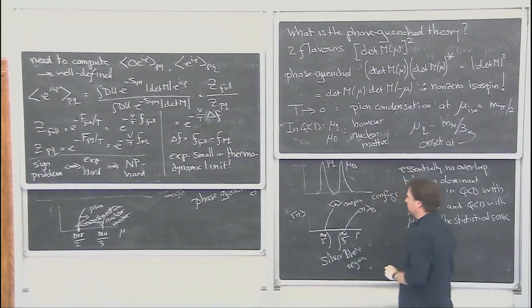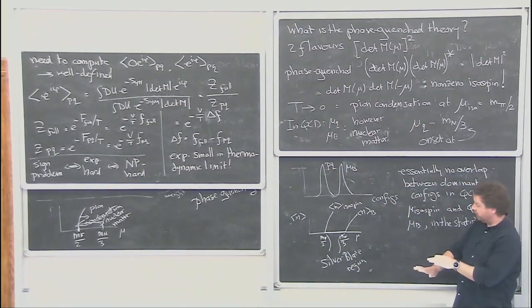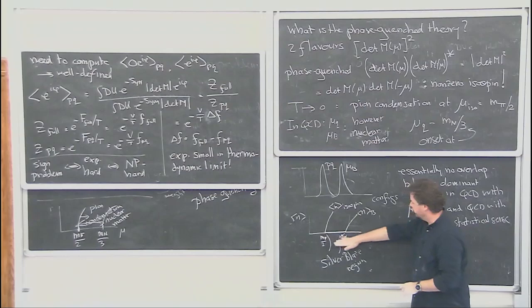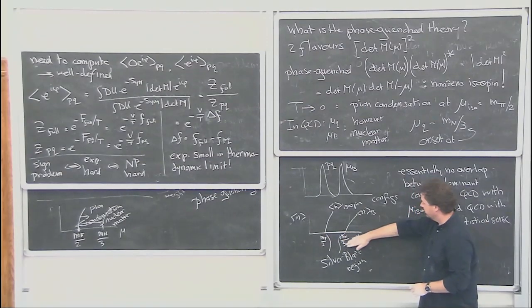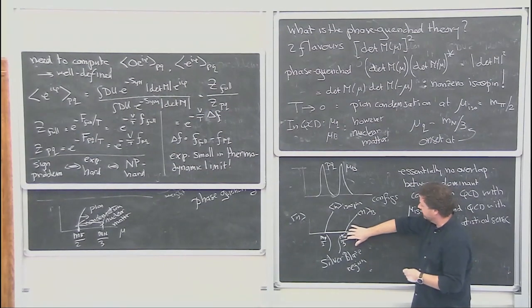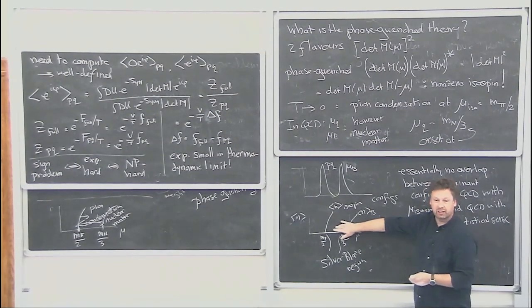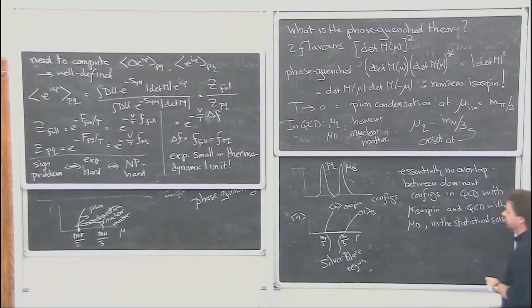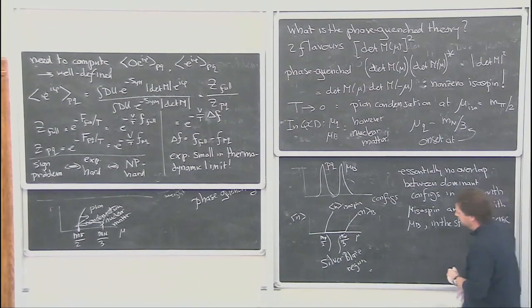Because what you want to see is nothing. You want to see nothing happening, no density of baryons, because I'm still below onset. But if you do it wrong, if your simulations do not capture the sign problems correctly, you will see an onset of something. And that's a sign that you've done something wrong. So that's the interesting challenge, in a way, that if you do numerical simulations, you want to get this region right.